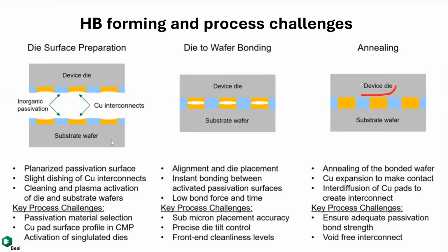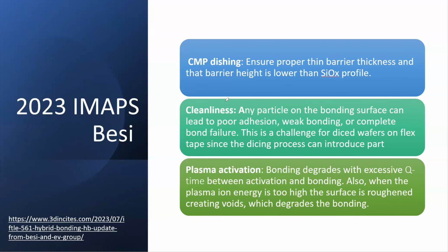Remember, the devices down here already have the backend process. They have a lot of backend process, with a maximum temperature of like 450. So if you're pushing to 300 to 400, they're not going to be happy. So this means that the void here has to be as small as possible, so you can use a lower temperature to get rid of the void by copper interdiffusion. All right, so this is what I meant. It has to be lower, but cannot be lower by too much.